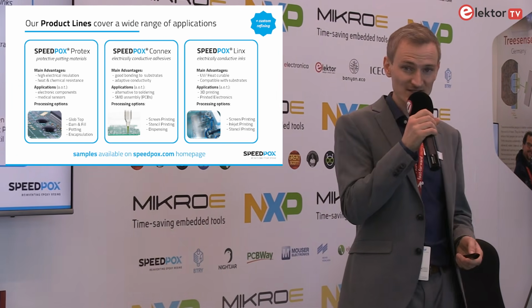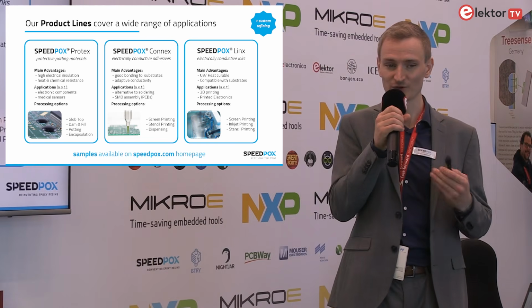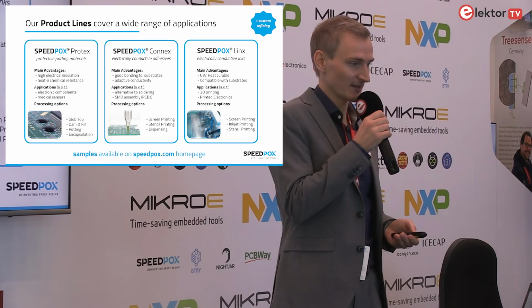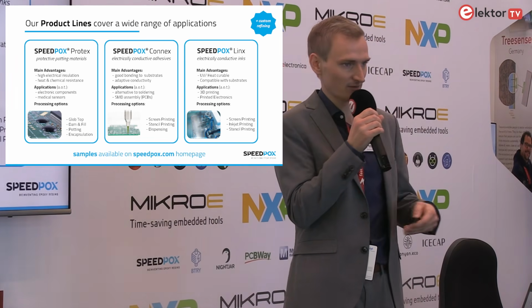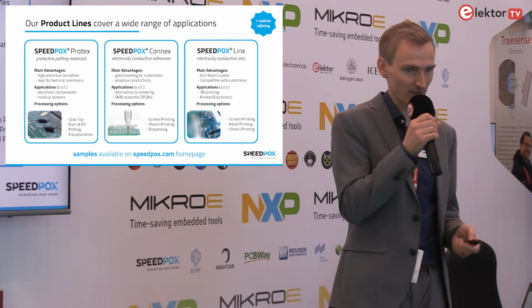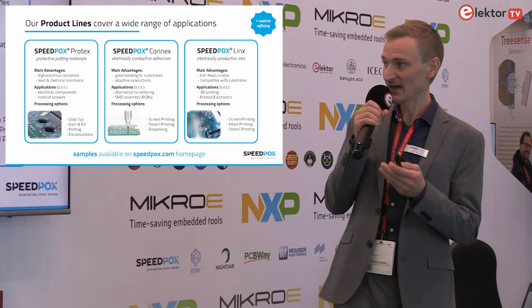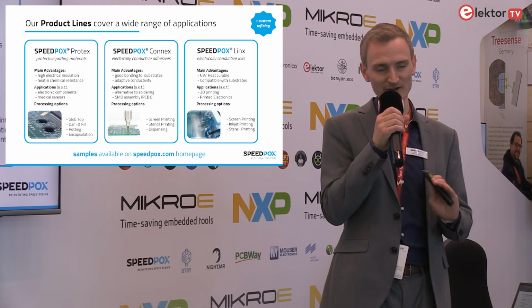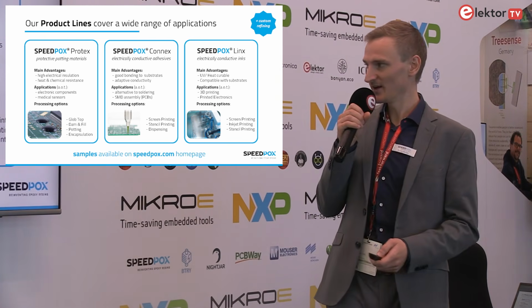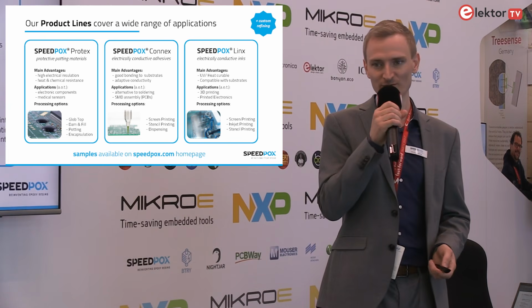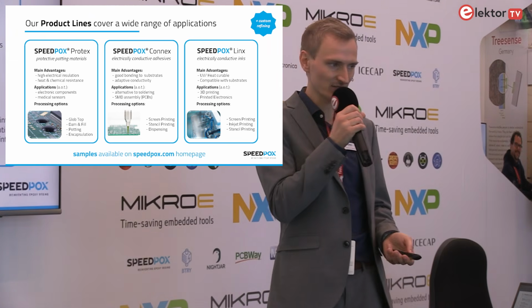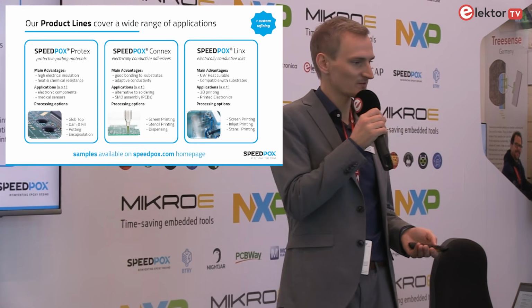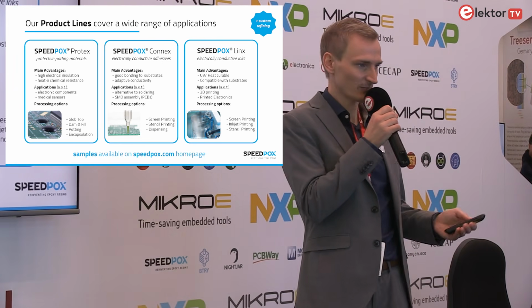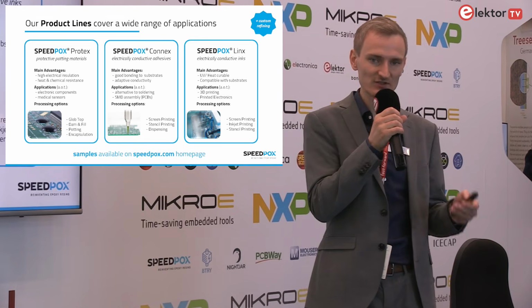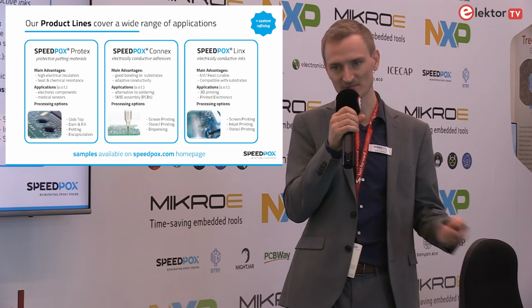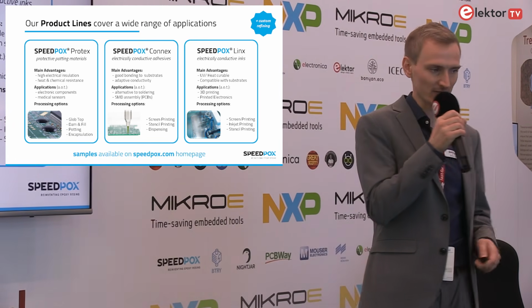Then coming to the Connex system, we can also produce conductive adhesives that are filled with carbon or silver-based flakes or nano fillers. And we can also cure them with UV, and that's a first in the market. We can use it to replace the traditional soldering process, but also for systems where additional heat would damage the sensors or the chips that you want to protect. So that's where our systems work fine.